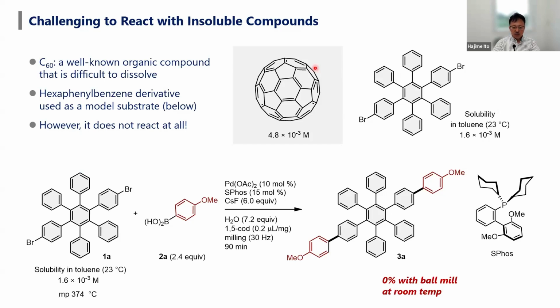But at room temperature, we cannot find any good yield of the products even after a long reaction time. We were disappointed, but we thought that cross-coupling reactions usually require a little bit higher temperature. Room temperature, in any case, does not give very good results.